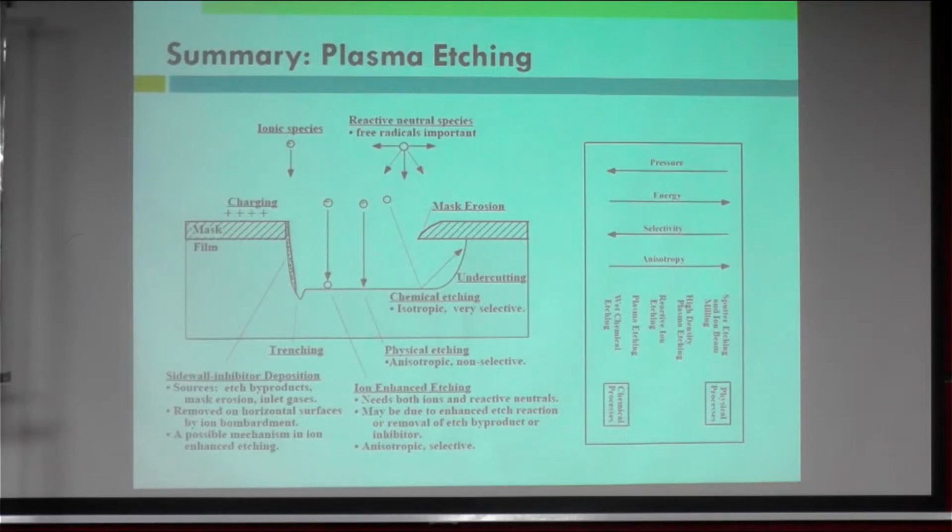So the control of the inhibitor process and the bombardment alternately: over time the inhibitor becomes thinner, then you deposit the inhibitor again, with the bombardment of ions to remove it, and the straight path can be achieved.